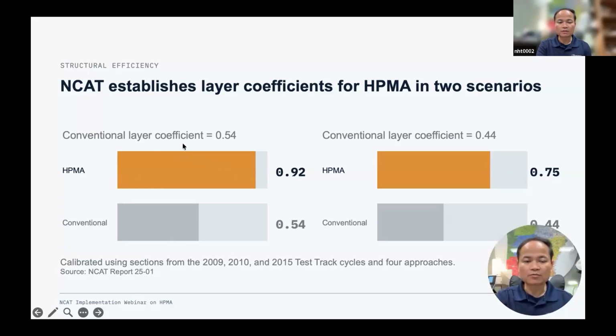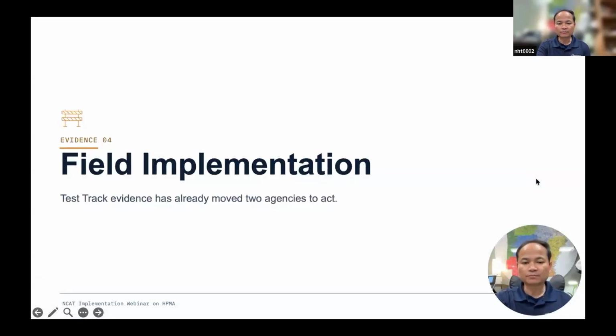So if the layer coefficient for conventional mix is 0.54, then the layer coefficient for HPMA will be 0.92. And then if the state is using maybe the typical 0.44, in this case, HPMA mix would have a layer coefficient of 0.75.